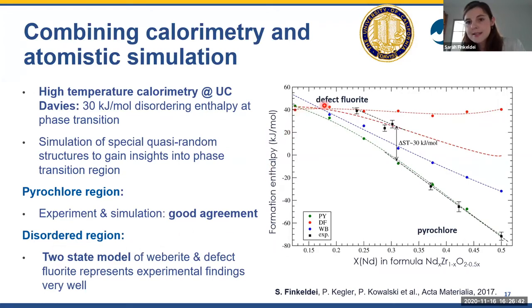And this is the dashed red line over here. And you can see that this describes fairly well the experimental findings in the defect fluorite area, and therefore confirmed our findings with a pair distribution function analysis that we are actually having different degrees of order in this disordered material. And we were also able to derive the enthalpy at the phase transition, so the enthalpy of disordering, to be 30 kilojoules per mole with the calorimetry experiments.